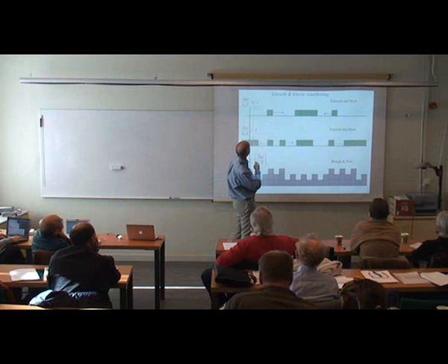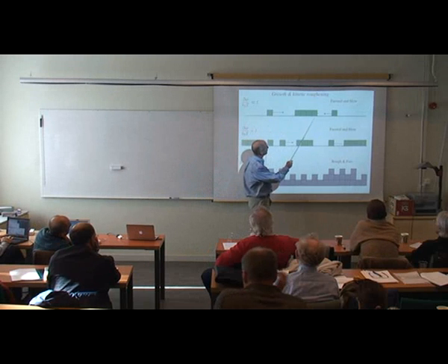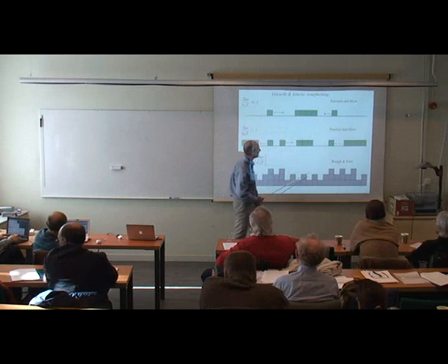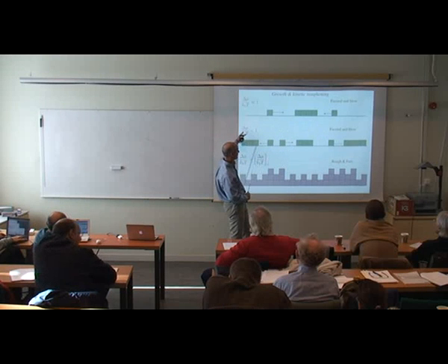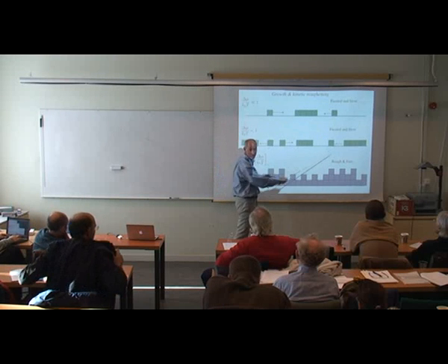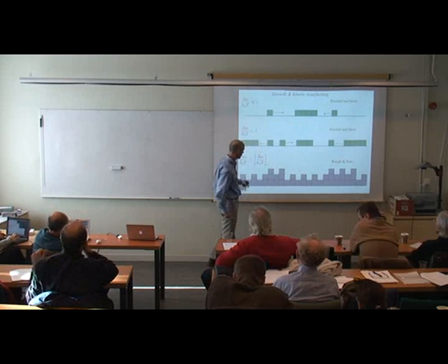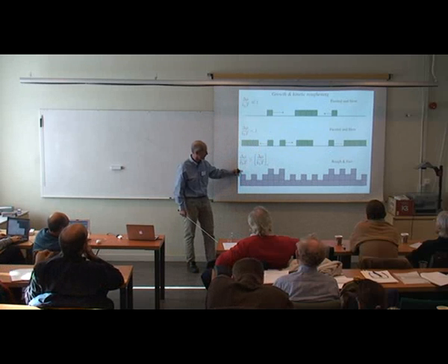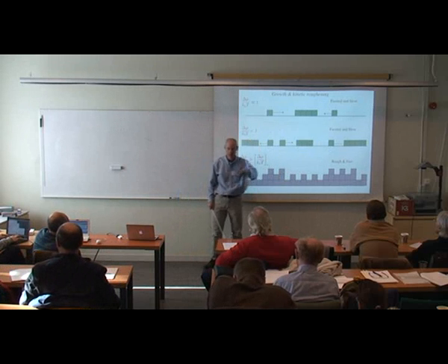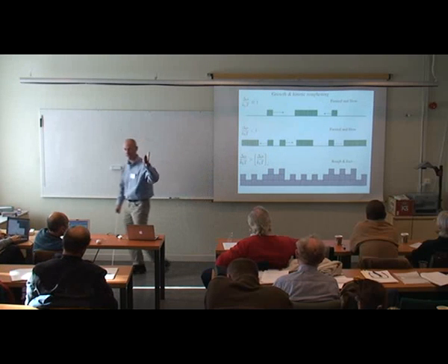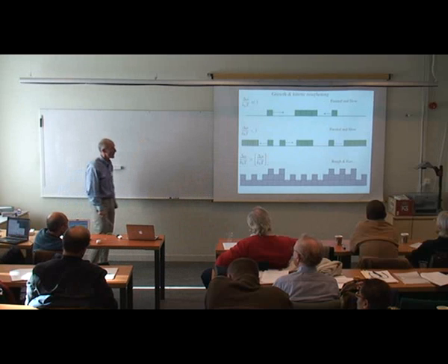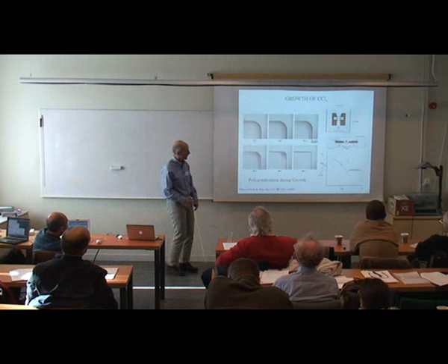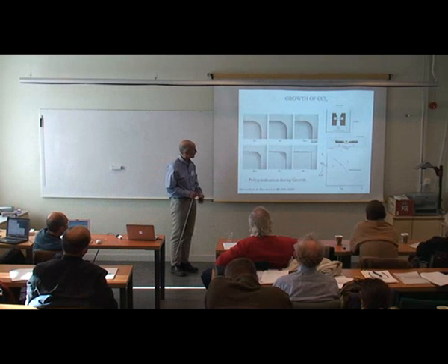But I can increase the growth drive. I add to this boundary, it creates a monolayer. As I continue to increase it, I can get multiple monolayers, okay, filling up, or multiple islands filling up a monolayer. And if I go above a critical value, it will roughen because the underlying material is buried. So we've heard KPZ and so forth. All right. So now, how does this work?